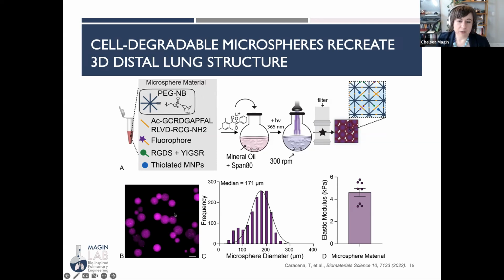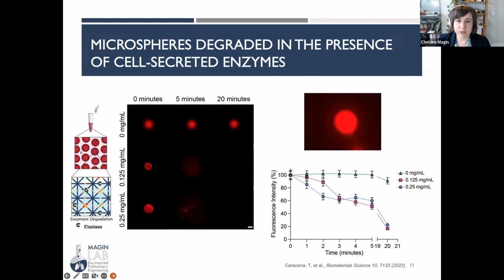We filter the microspheres to make sure our average microsphere is about the same size as a human alveolus, which is 200 microns in diameter. And then we did some testing to make sure the elastic modulus or the stiffness of our hydrogels was within the range of healthy lung tissue, 1 to 5 kilopascals. These microspheres can be degraded in the presence of cell-secreted enzymes, and I just wanted to show you a demonstration of that here. So we added in enzymes to our cell culture mixture, and you can see that we start out with microspheres at 0 minutes, and these degrade over time, and it's shown here in the video as well.